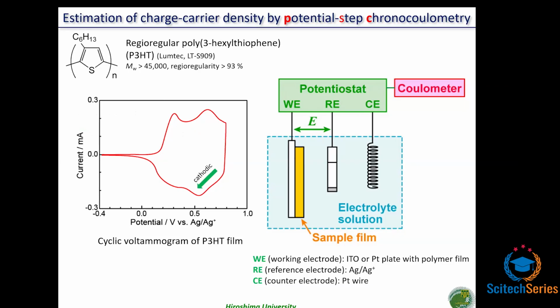When the potential is reversed to the negative side from 0.8 volt, cathodic current was observed. It suggests that the electrons were returned into the oxidized polymers. Finally, when the electrode potential drops to around 0 volt, the electrons are completely returned to P3HT and no current was observed anymore. And then P3HT returned to a neutral state.